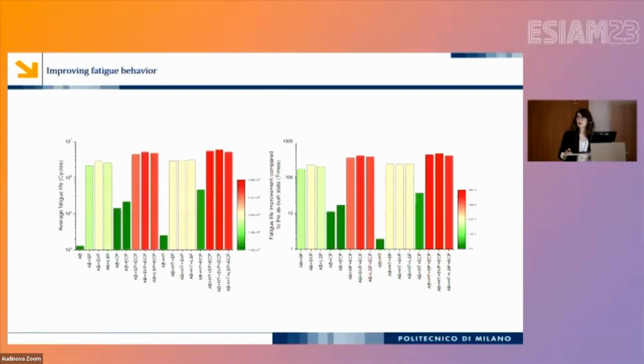And finally, we performed rotating bending fatigue tests at a fixed stress level on these samples in order to compare the fatigue life that we could get from each of these treatments. Here you can see the as-built sample that has a very poor performance. And then after the heat treatment, we are already improving the fatigue performance because we are homogenizing the microstructure and releasing the tensile residual stresses. But then with the other treatments, as we are changing the surface roughness and inducing also compressive residual stresses, we are considerably increasing the fatigue performance of the part, and especially with the hybrid treatments, where we are combining the severe plastic deformation based technique followed by an electrochemical or chemical polishing.